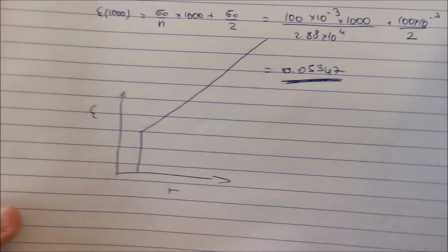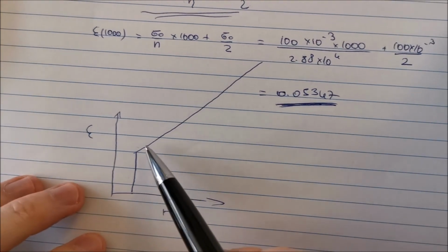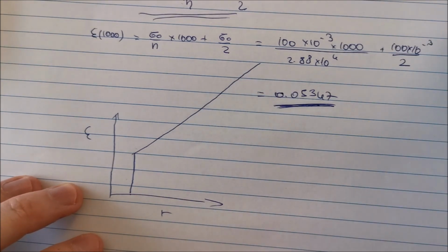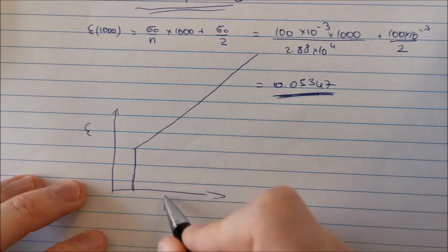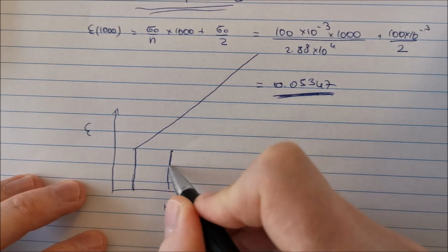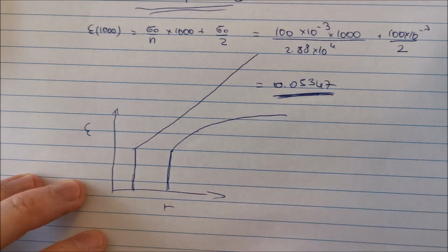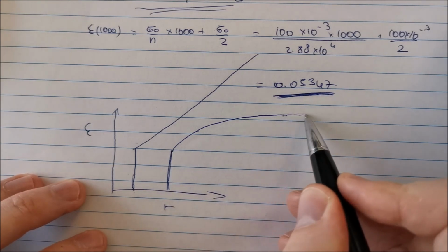So what does that mean? It means that this system is probably not suitable to describe a creep test, right? Because no biopolymer will have the strain increase over time linearly like that. Typically, for a polymer, you would have an instantaneous rise, and then a logarithmic-like increase over time until you reach a plateau.